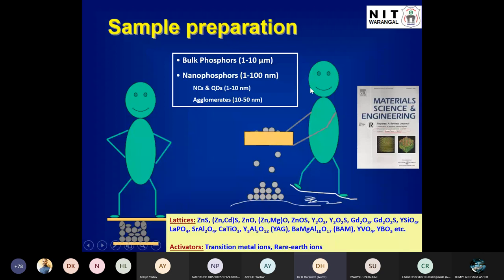Okay, so if you make powders and if you make phosphors in bulk size, meaning the size of the phosphor material is from 1 to 10 micrometers, you can call them bulk phosphors. And if the size is in nanometers, 1 to 100 nanometers, then you can call it nanophosphors, the same material. And if it is still less, like 1 to 10 nanometers, you can call it quantum dots and nanocrystals and so on. Whereas if it is 10 to 50 or 10 to 100, then you can have agglomerates. Agglomerate is a combination of various small particles, like a motichur laddu. So you have all small things attached at a single place. That's an agglomerate.